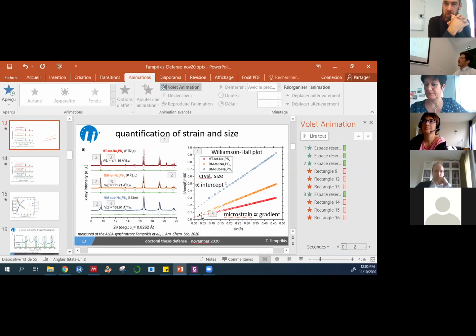Yes, I'm following what you're saying. The reason why I did it like this with an isotropic strain and size, and I was happy with it, and I left it at that, is because I got a decent fit basically like this. I tried introducing preferential orientations for both strain and size. Did not really get an improved fit, but all of the analysis I did was on the complete diffractogram and not line by line like you're proposing. I did not see the reason to do so.